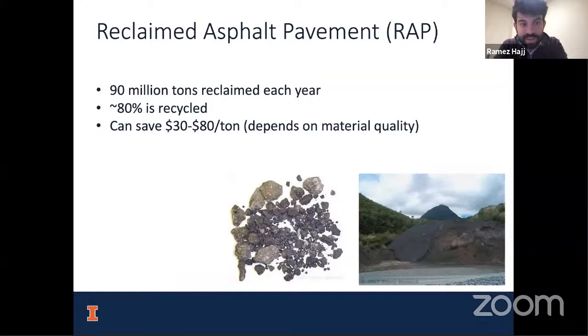Based on this, we can have a cost savings of $30 to $80 per ton, which is pretty huge. But this is quite a large range and really depends on the material quality. More importantly, we can make a huge impact from a sustainability perspective. So when we reclaim the old pavement, we can prevent the need to produce more asphalt. And the more reclaimed pavement we can use in the asphalt mixtures, the less we have to rely on distillation of crude oil, which of course is a process that leads to huge carbon emissions, a very big carbon footprint, and is generally not a sustainable practice. So we like to reclaim asphalt. We hope that it's sustainable.